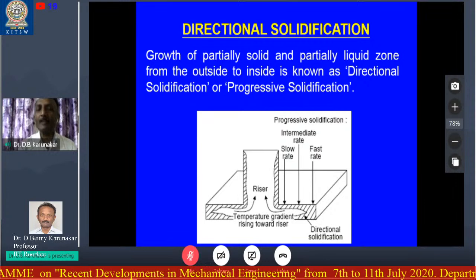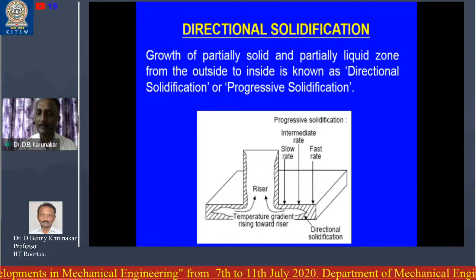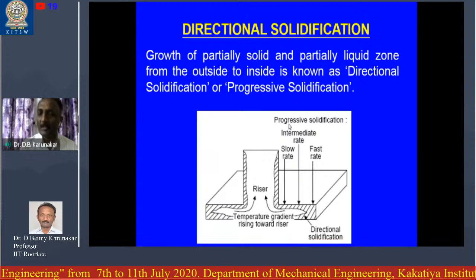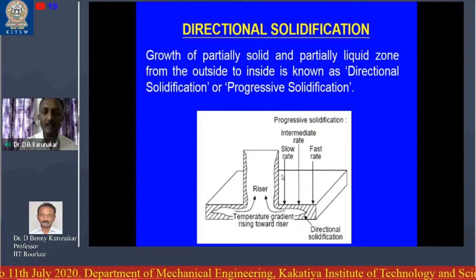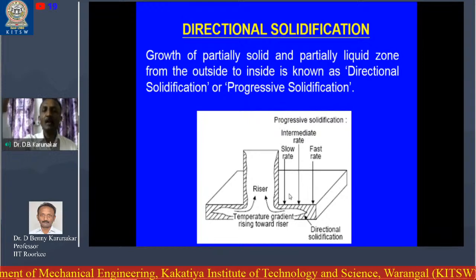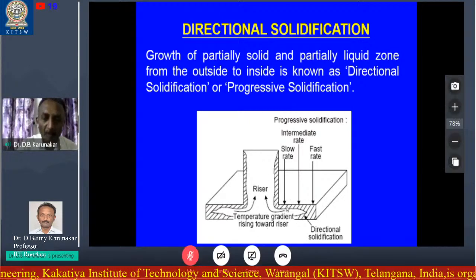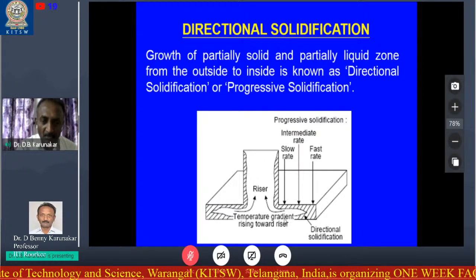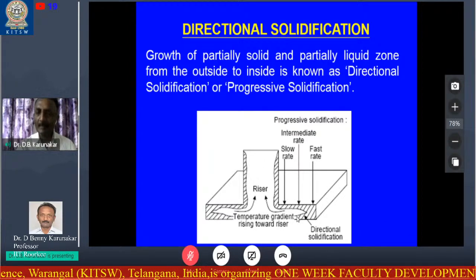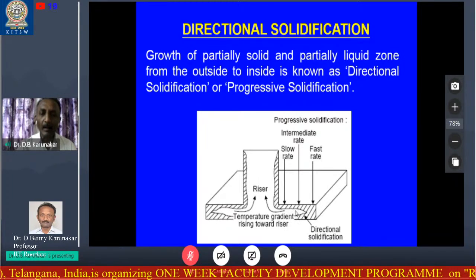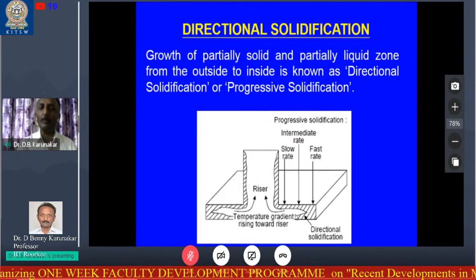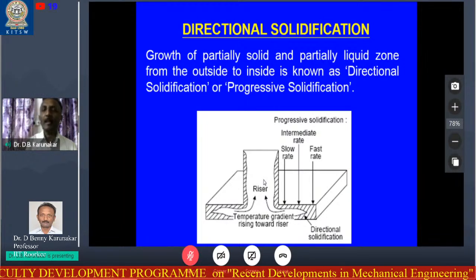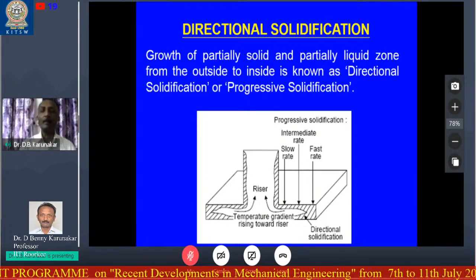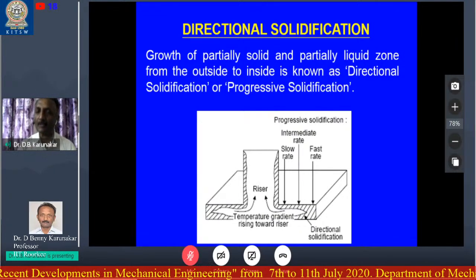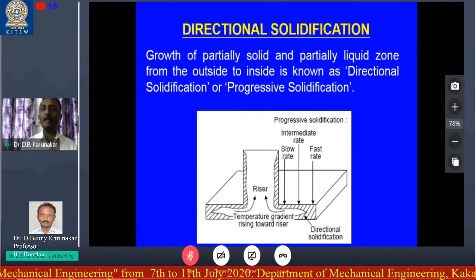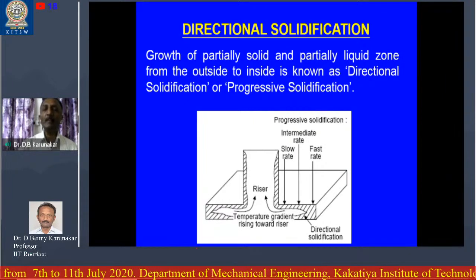Either the directional solidification or the progressive solidification. Just imagine there is no directional solidification, only progressive solidification, and it's starting from top to bottom, solidifying as it comes down, suppose it closes here. Imagine here there is a region which is not solidified, and the riser is still having liquid metal, but it is not able to supply because somewhere the progressive solidification has dominated and it is not allowing the liquid metal to reach the area where there is shrinkage.